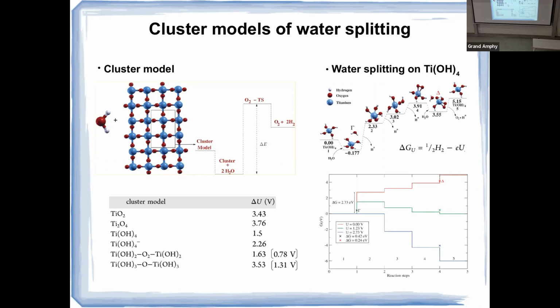You have DFT computed energies complemented by a thermodynamic model to include the external potential. And I will go directly. So the idea, the overpotential, is we compute the minimum external potential we have to apply, the potential bias we have to apply to make this free energy path downhill. So when you apply this potential from there, it's